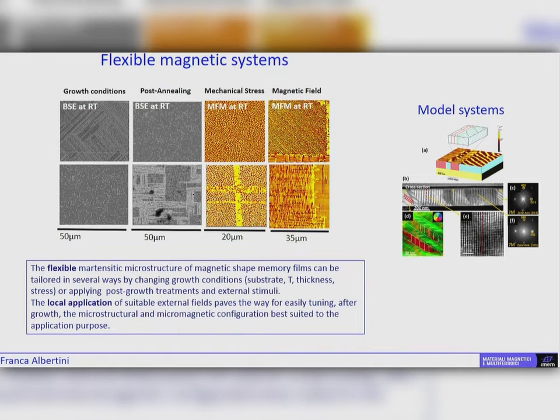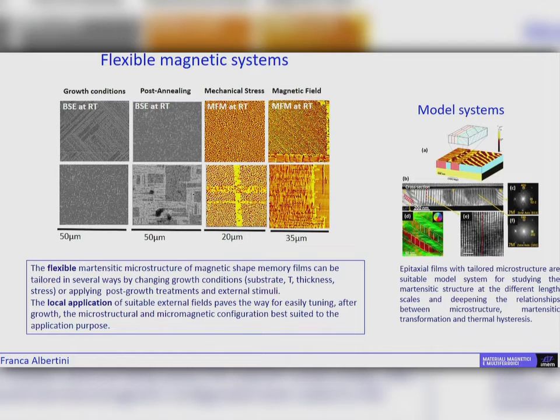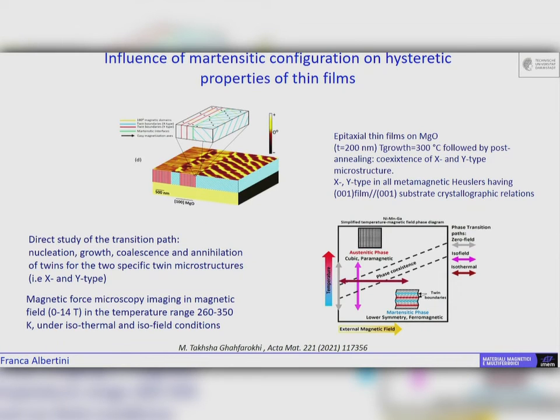On the other hand, thin films are a very good model system to study the structure of these materials from the atomic to the micro scale. And by taking advantage of a film where we had both microstructure X and Y, so both kinds of microstructure, we have made an experiment in high field to study directly the role of the two different microstructures on the Martensitic transformation.